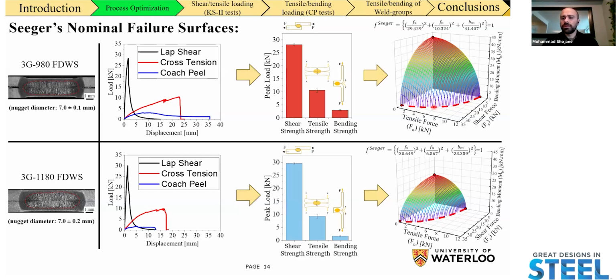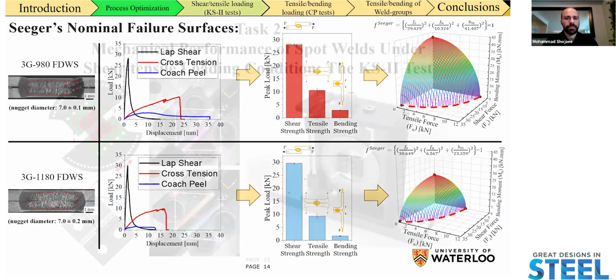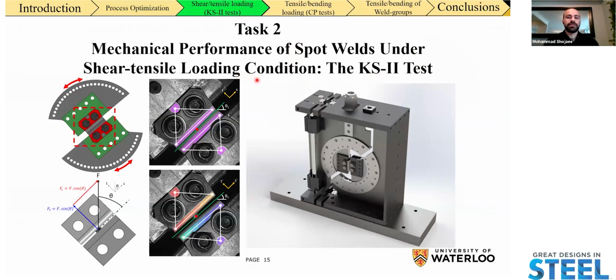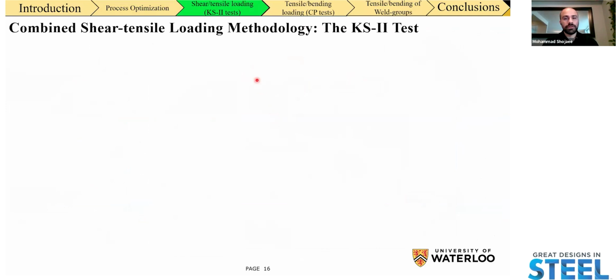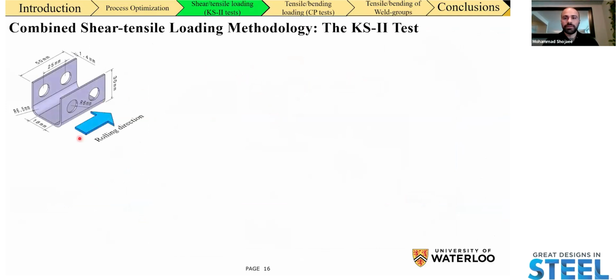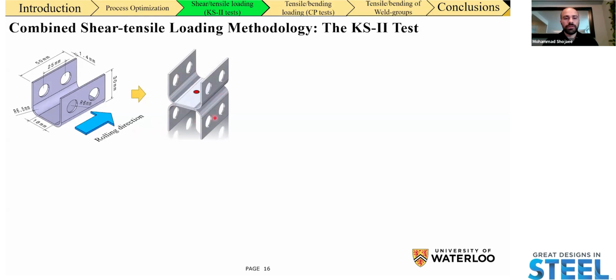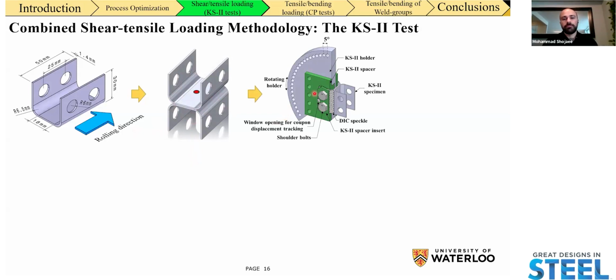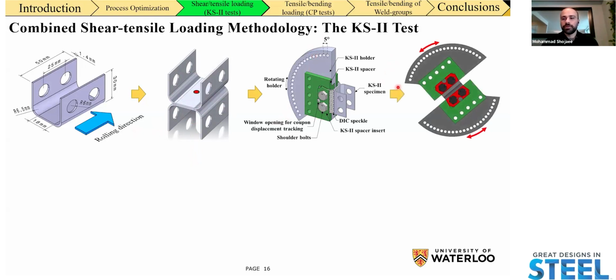So let's start off by looking at how accurate the failure surface is in the shear tensile loading domain, which is the dashed red line at the bottom of these failure surfaces. For that, as I mentioned in the beginning, we performed the KS2 test at intermediate loading conditions or various shear and tensile loading ratios. You can see the methodology for the KS2 test in this slide. It is comprised of a U-shaped coupon with the dimensions shown here. We joined 2 of these U-shaped coupons together with the spot weld at the mating interface between the 2 coupons, and the coupon itself is mounted on a holder with different components, and this holder is able to rotate and accommodate different ratios of shear and tensile loads being applied to the spot weld in 5-degree increments, as shown on the right-hand side.